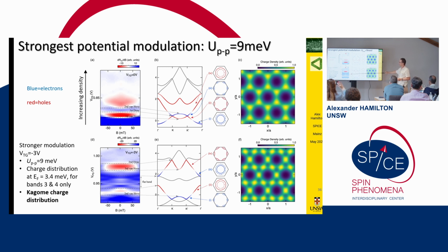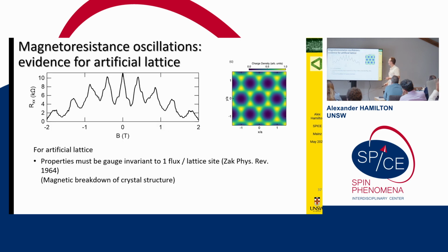If you just calculate the charge distribution for these two bands here, you get this charge distribution, which is, of course, a Kagome lattice, which is no surprise because this is the band structure of a Kagome lattice. So we can tune from honeycomb to Kagome charge distributions. And this is where it gets really cool.